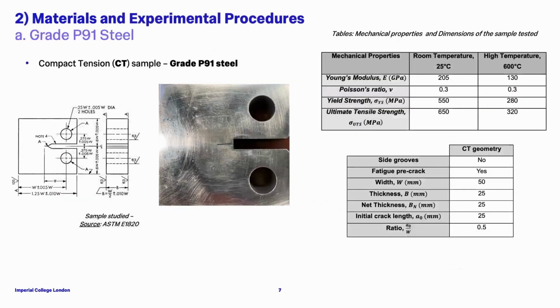So as I said, I did my toughness test at 600 degrees on CT samples made of P91 steel. They were quite thick, 25 millimeters for the thickness, with no side grooves, because the really small samples the PhD student used did not have side grooves. The width is 50 millimeters and the initial crack length is 25.